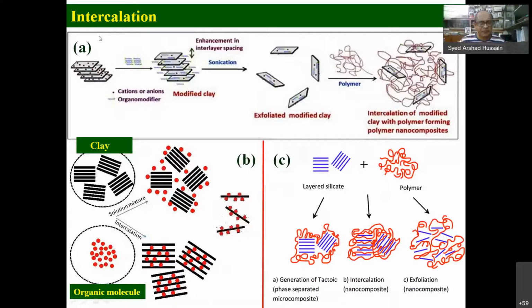And then intercalation: it's possible to incorporate different materials within the clay layer or on the surface also. This is just a schematic. One can put this material inside the layer, or maybe in the swelled system. This is a single sheet, so one can incorporate the material on the surface. This is also possible. This is, say, some polymer intercalated in the clay sheets. Here you can also see some clay crystals. It's possible to intercalate at the edge areas also, in between the sheets also. So in this way it's possible.